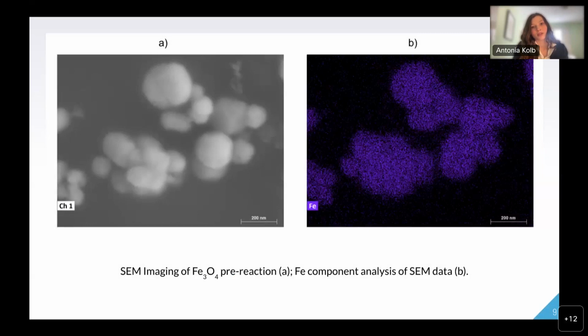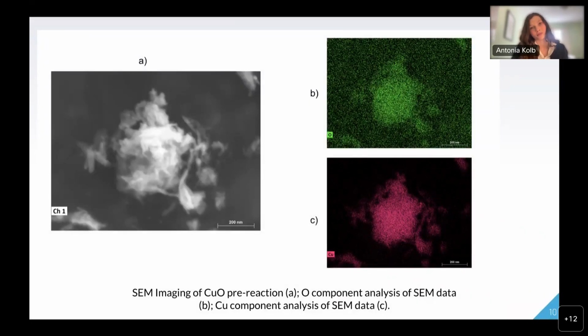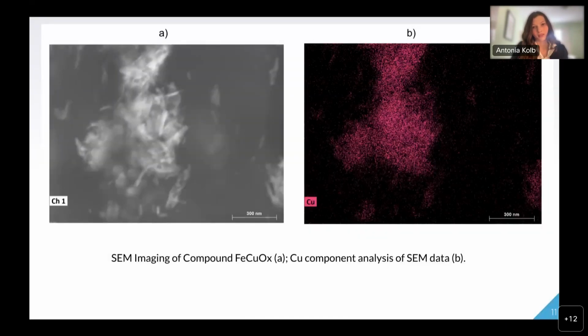The scanning electron microscopy, or SEM, data showed correct pre-reaction morphology, seen here in the component analysis. This was the SEM imaging of the magnetite pre-reaction, and this was the copper oxide pre-reaction. After the reaction, the morphology of the compound displayed the presence of copper, indicating that a reaction had occurred.